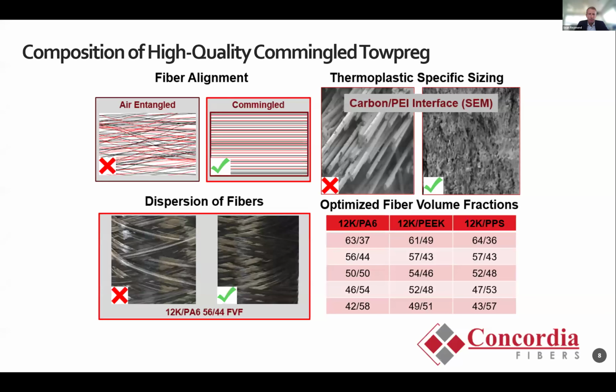The pictures in the lower left again show the striping in the left picture versus the uniform color in the right picture, and again highlight how we control the blending of the fibers. And then the table on the lower right shows potential fiber volumes that we can achieve with PA6 or PEEK or PPS using a 12K. These are our standard volume fractions. We can make other fiber volumes with some planning as well.